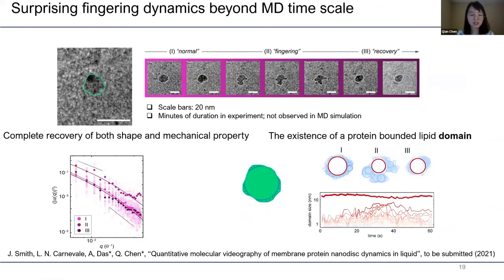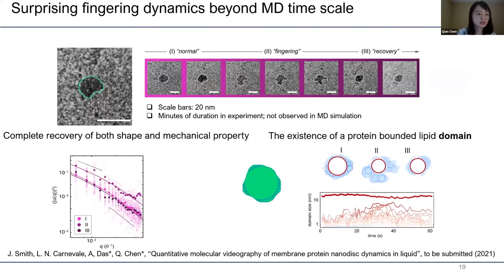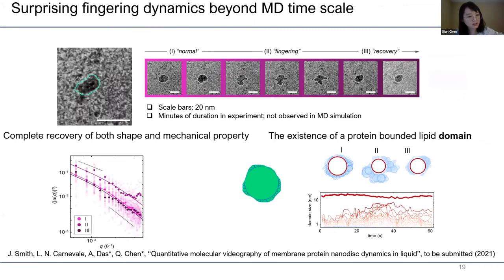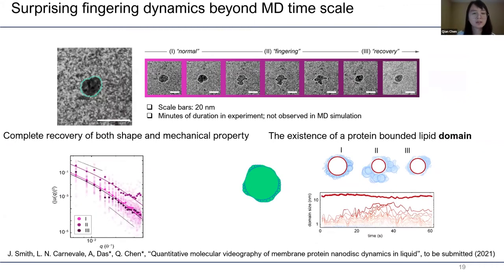And lastly, if we allow the nanodisc to relax for a longer time, we can see surprises. Shown here, they can form into fingers and then come back to their regular circular shape. I should mention this observation is only possible during our minutes of duration in experimental observation. It's not really observed in our MD simulation, possibly due to the limited time scale there. We can also do the same Fourier transform analysis for stage 1 and stage 3. Their data perfectly overlap with each other, which shows there is a complete recovery in both the shape and also the mechanical property of the nanodisc.